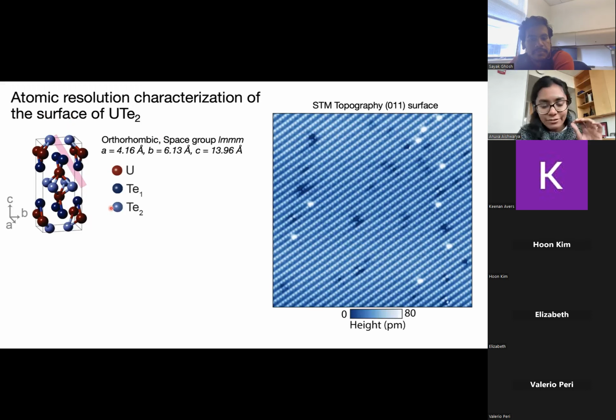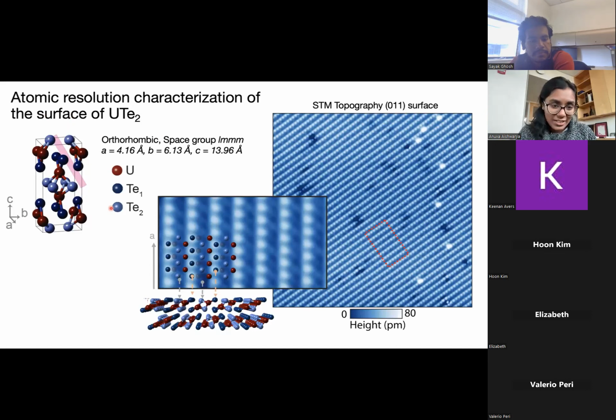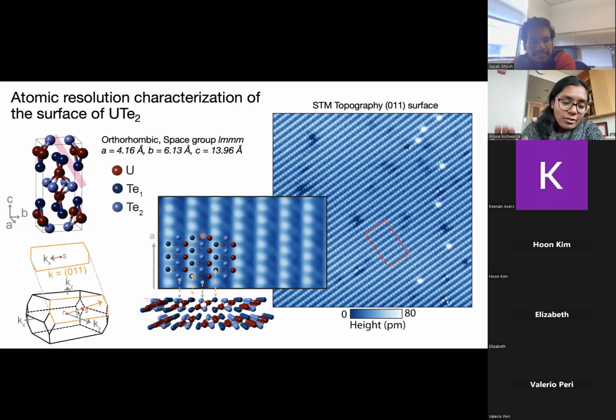If we take a close look, we can see that we're seeing two kinds of atoms. One is brighter than the other. That is because the tellurium 1, which is the darker one, is slightly more projected to the surface than the tellurium 2, which is the blue one. Based on this, we can identify the positions of the tellurium, and the uranium is underneath, so we don't actually see it. The tellurium orbitals are also slightly bigger, so we mostly see the tellurium atoms. And for people who are interested, this also gives us access to the orthorhombic (0 1 1) facet of the Brillouin zone.